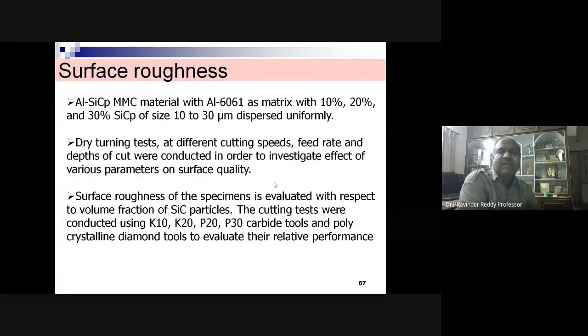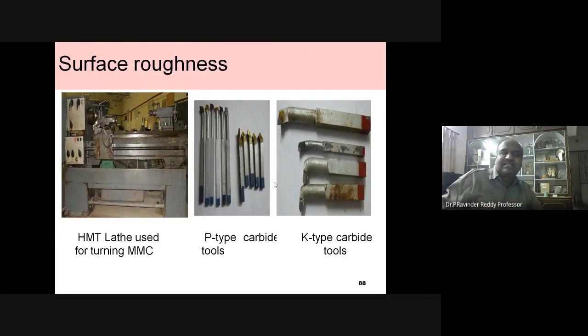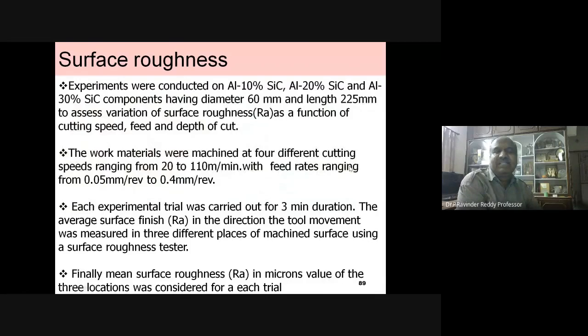The aluminum silicon carbide particulate MMC material with aluminum 6061 as matrix with 10, 20, 30% silicon carbide particulate of size 10 to 30 micron dispersed uniformly. Turning tests at different cutting speeds, feed rates, depths of cut were conducted in order to investigate the effect of various parameters on surface quality. Surface roughness of the specimens is evaluated with respect to volume fraction of silicon carbide particulates. The cutting tests were conducted using K10, K20, P10, P20, P30 carbide tools and the polycrystalline diamond tools to evaluate their performance. The P-type tools and K-type tools showcased the results obtained.